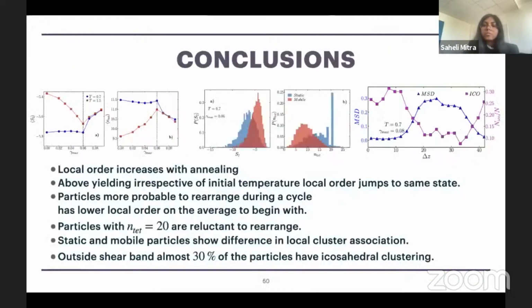To conclude from this part, what we have seen is that local order in the system increases with annealing. Above yielding, irrespective of their initial temperature, the local order jumps to the same state. Particles that rearrange during a deformation cycle had lower local structural order to begin with, on average. Particles which are involved in 20 icosahedral and 20 tetrahedral clusters are reluctant to move as we shear the system. The mobile and static particles have very different types of local structural environment, as we found from TCC analysis. And in the presence of a shear band, outside of the shear band, almost 30% of the particles are involved in icosahedral clusters, whereas inside the shear band, this percentage drops to 0.